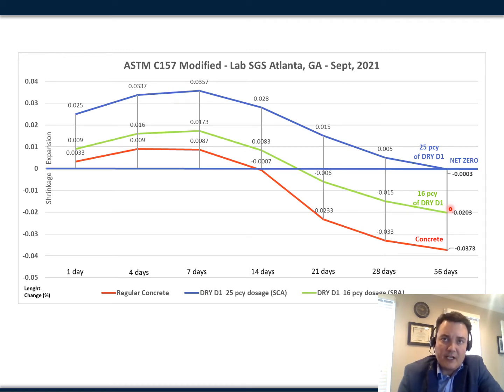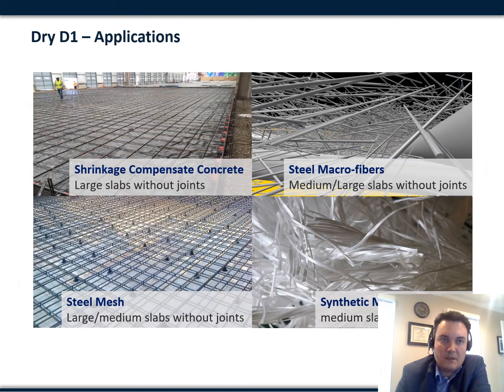But if you use 25 pounds per cubic yard of DRY D1, you're going to have a sharp expansion, and then a smoother shrinkage starting after 7 days. You're going to achieve net zero after 40 to 56 days. It's a big deal. It's 4 times less volume than expansive cement. And DRY D1 can be used with any system or mix design: slab-on-grade, steel and synthetic fibers, steel mesh and rebars, post-tensioned or pre-stressed, any system.